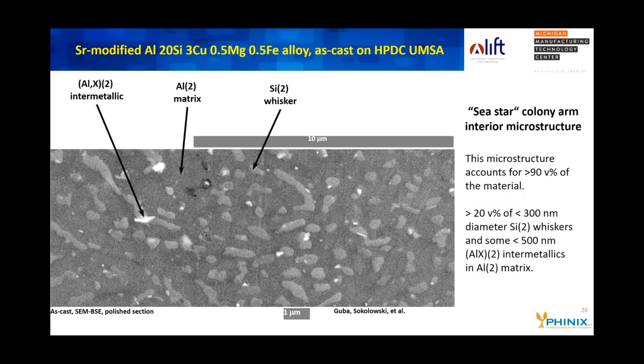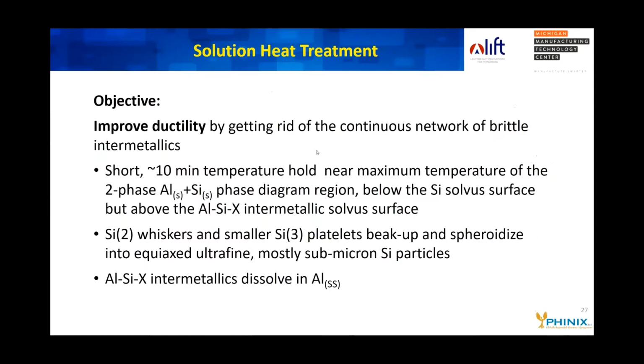If you section and polish the section through this sea star colony arm, you can see that there's not only silicon whiskers there, but also some very small fragments of intermetallics that are also less than 500 nanometers in size. And the key point here is that this is the structure that dominates the volume of the entire material and accounts for about 90% of the volume. And the rest is the colony boundaries.